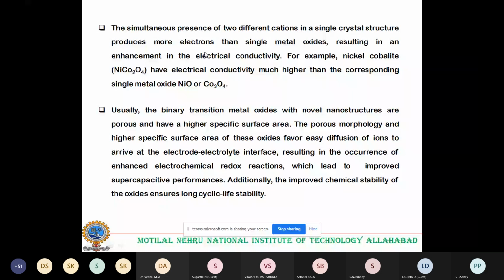The second, usually binary transition metal oxides with novel nanostructures are porous and have a higher specific surface area. The porous morphology and the higher specific surface area of these oxides favor easy diffusion of ions to arrive at the electrode-electrolyte interface, resulting in enhanced electrochemical redox reactions, which leads to improved capacitive performances. Additionally, the improved chemical stability of the oxide ensures long cycle life stability.